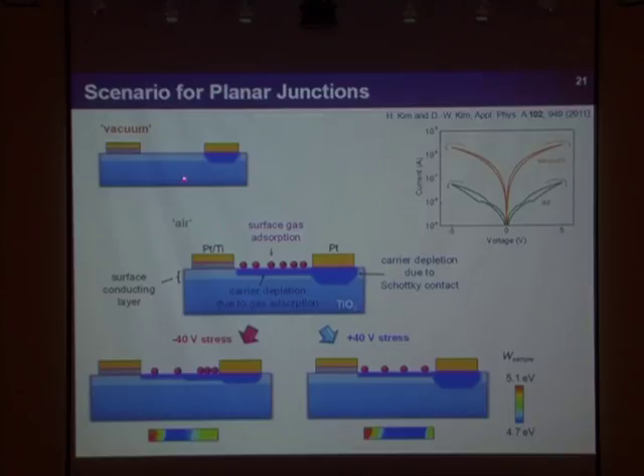And if we put the sample in air, oxygen gases will absorb, and as I told you, they will deplete the surface region. Carrier depletion can also be expected under the platinum electrodes. After applying minus 40 or plus 40 volts, somehow the amount of absorbed gas is reduced, and that will cause the work function change in the bulk region.